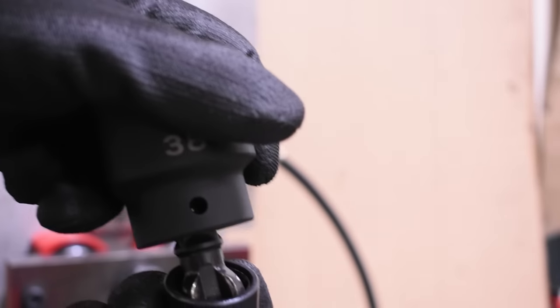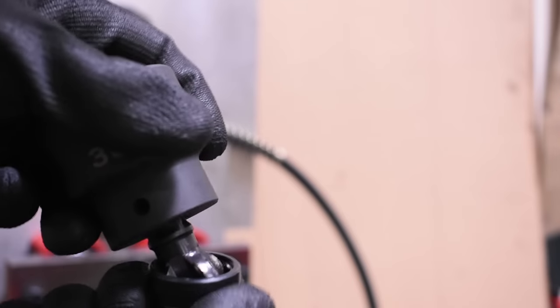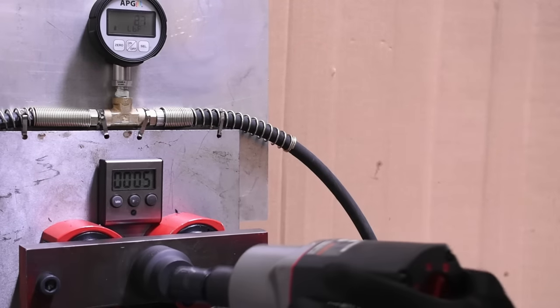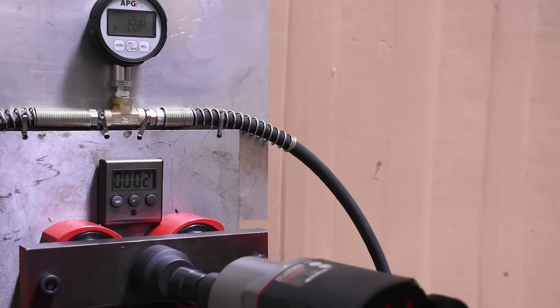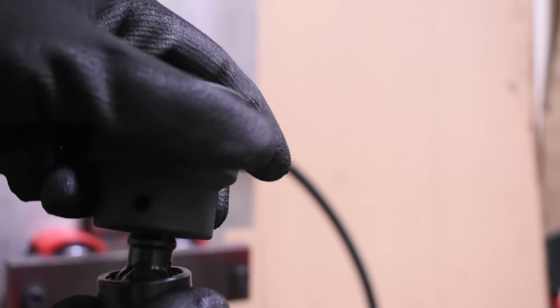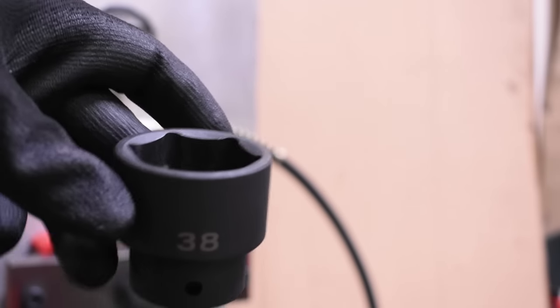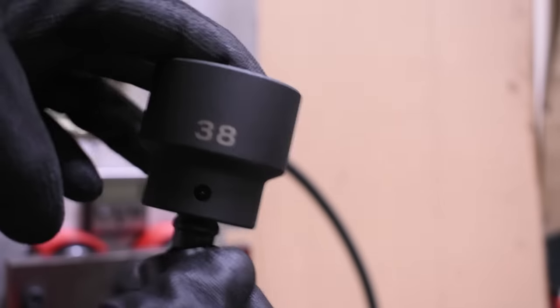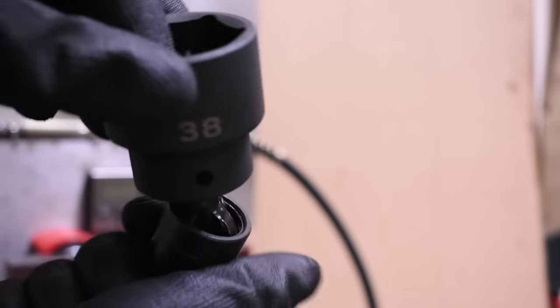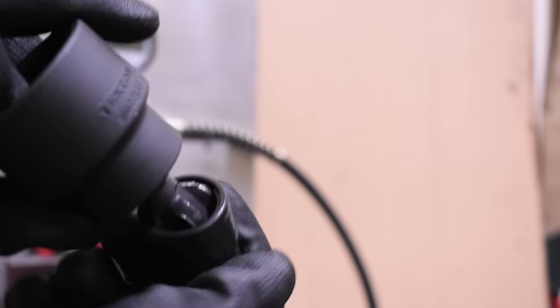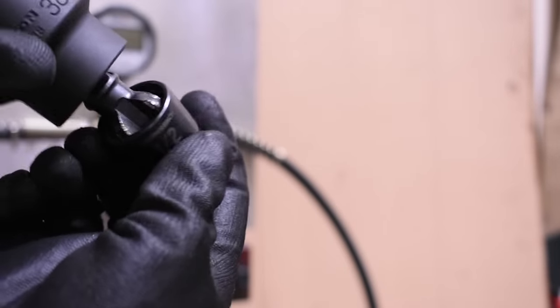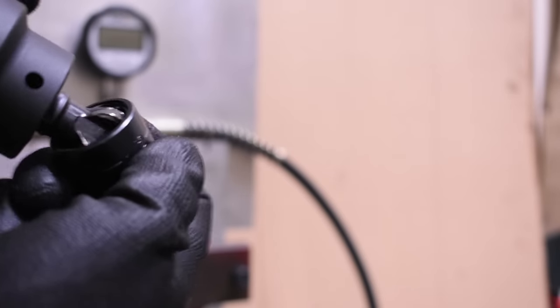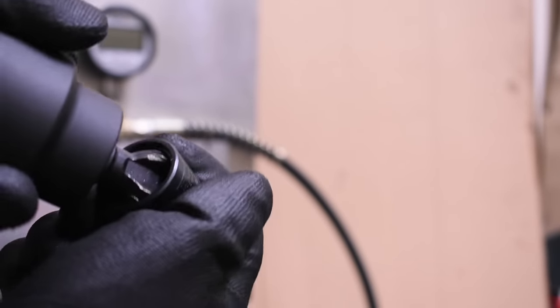The GearWrench X-Core got beat to heck. Not sure if you could tell from the clip we showed, but it has a lot of back and forth movement while in use compared to the others. And as soon as we moved the angle around on this thing while it was impacting, it started spitting chips and dust all over the workbench like it was puking its guts out. It was definitely not happy to show up for work today. You can see from the results here mushroomed over edges. Every lobe has small chips and nicks and material missing from it altogether.